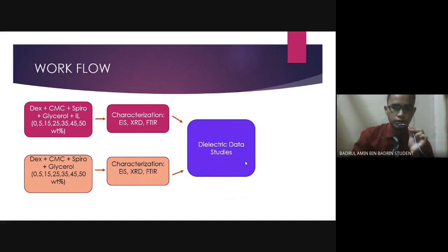The method used is the solvent casting method, in which the polymer is blended until a homogeneous solution is achieved, and then dried in an oven for 3 or 4 days at 60 degrees Celsius and peeled off afterwards for further studies. So the first system is the mix of the 4 elements. The highest conductivity achieved will be used for the second system. Then the end of the workflow is dielectric data studies.